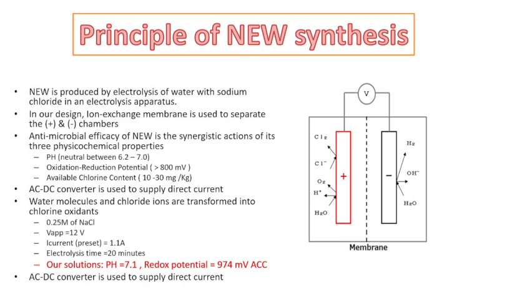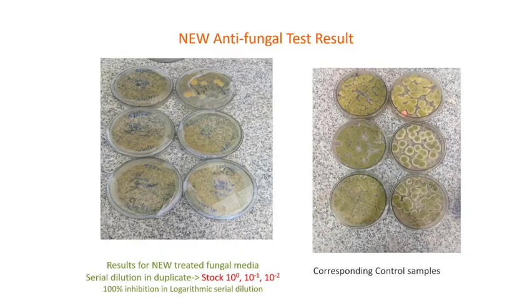With this, the most impact comes from the synergistic effect of the pH, the redox potential, and the available chlorine content. Once we prepared this, we tested duplicate samples at 10 to the power of 0 for the stock solution, and then by serial dilution down to 10 to the power of -2, and in all of the cases there was 100% inhibition of the growth of the fungus, compared with the corresponding control samples. And as you can see, the control grew.